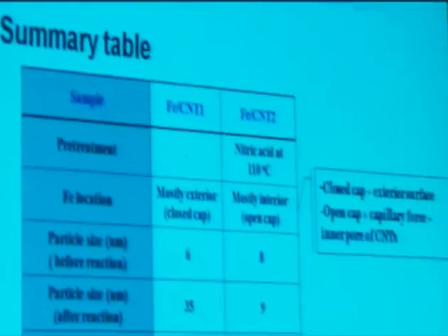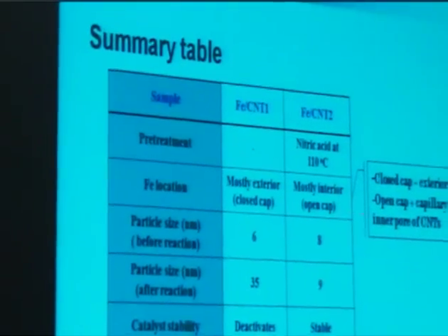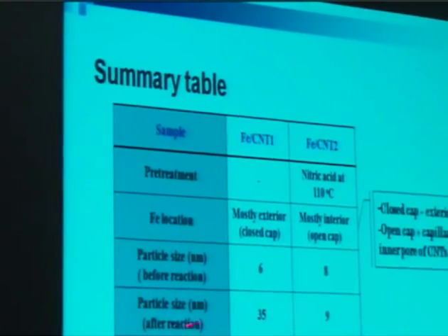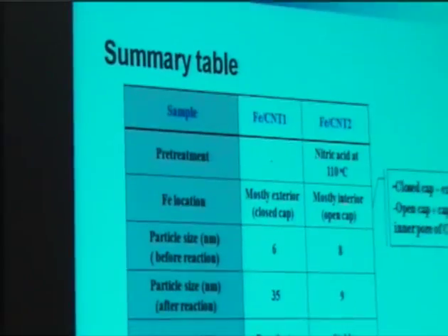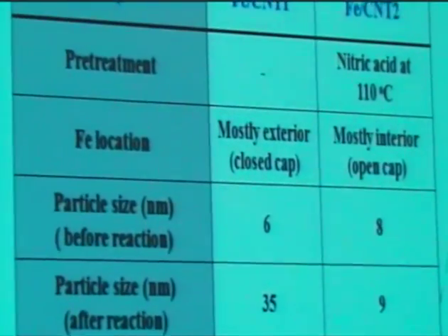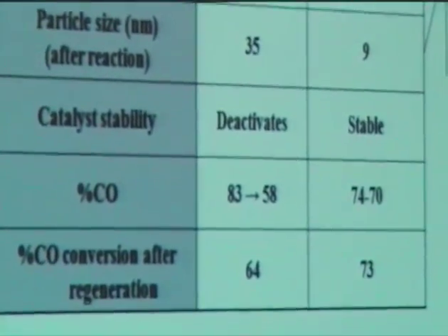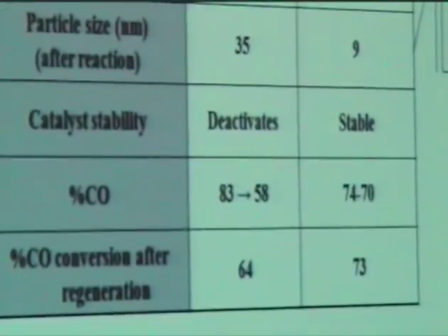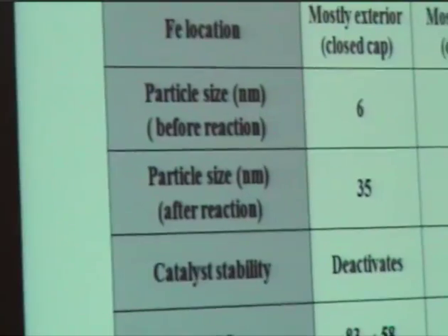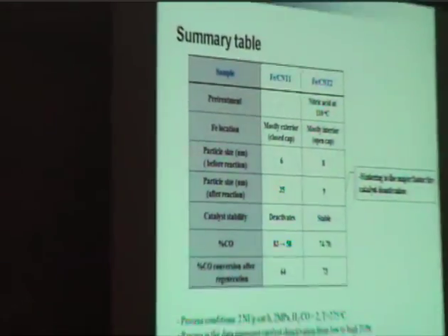CNT1, the closed cap, has most of the metal particles on the exterior surface. With the open cap plus capillary force, the metal particles are inside. After reaction, we can see a significant increase in the metal particle size. So we have enough evidence to say that sintering is the major factor for deactivation when we are using nanotubes.